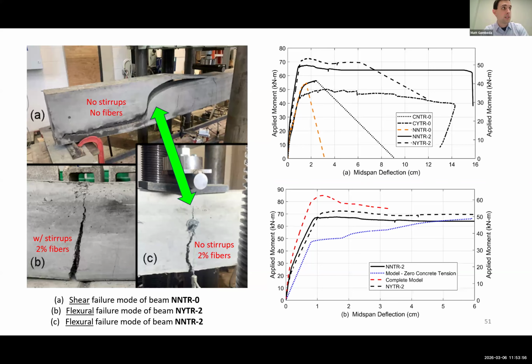So the results here are telling us that the experimental result is bounded by the complete model, where the tension is engaged perfectly without any little defects in the beams or anything that could cause it to be slightly lower strength. And then the blue curve is where we wouldn't have any tensile strength considered at all. So we're actually bounded nicely between those 2 curves, which I thought was a favorable result.